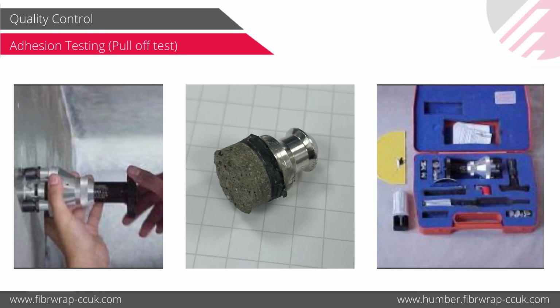So when we've finally done the test, as part of our QA/QC procedures, we have two tests that we look at. Because it's a bond critical application where we are relying on bond between FRP and concrete, we do a pull-off test, which is the test all the project engineers should ask the contractor to do if there is a bond critical application, which could be a beam strengthening, slab strengthening, wall strengthening.